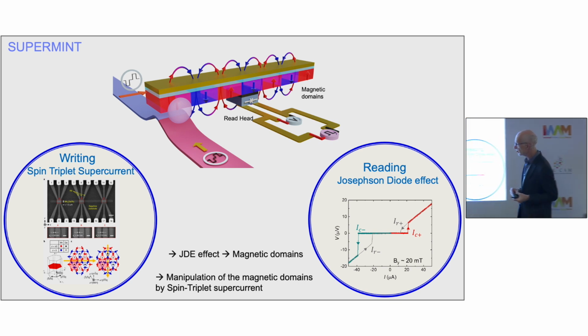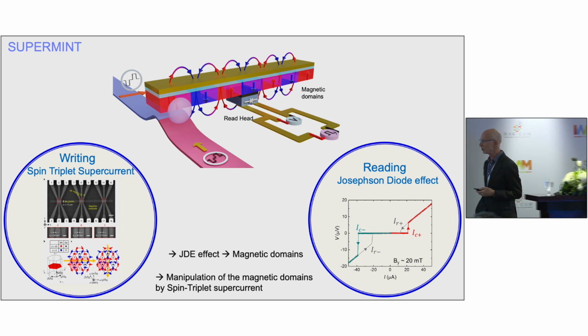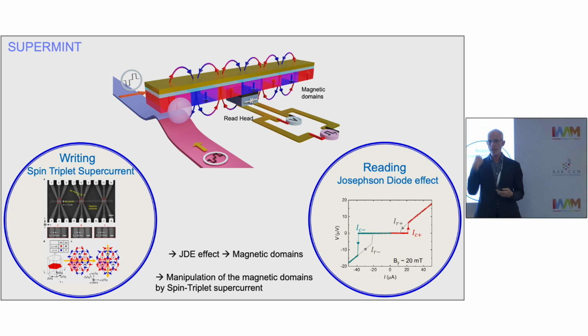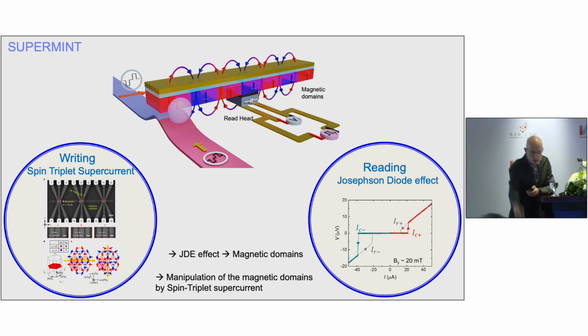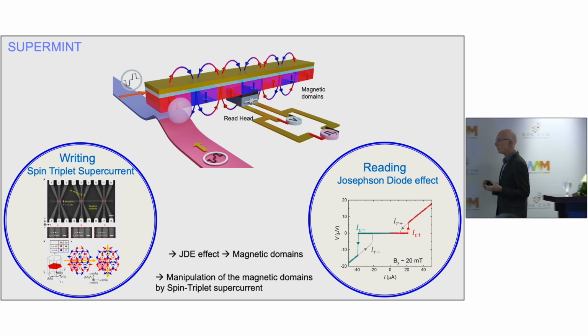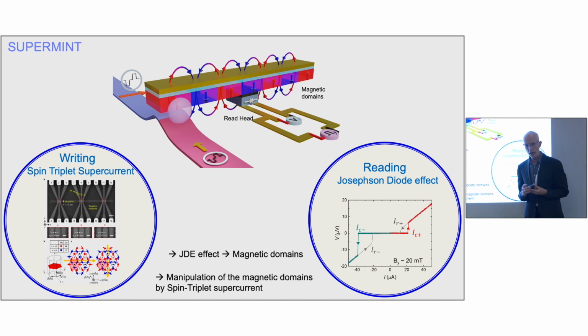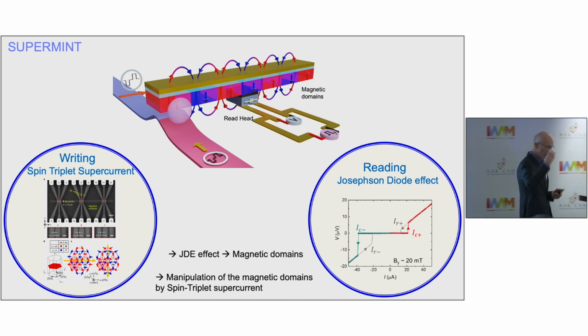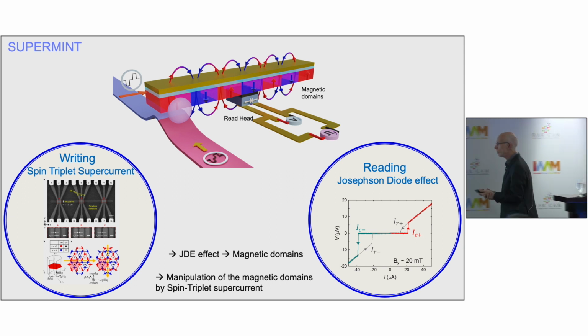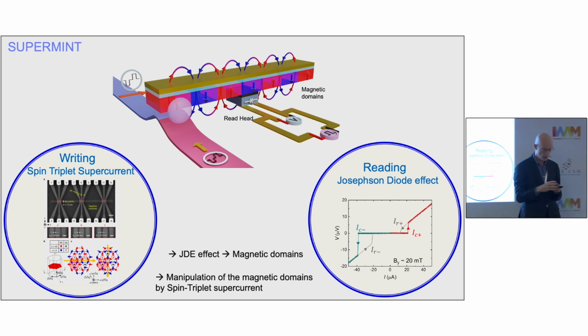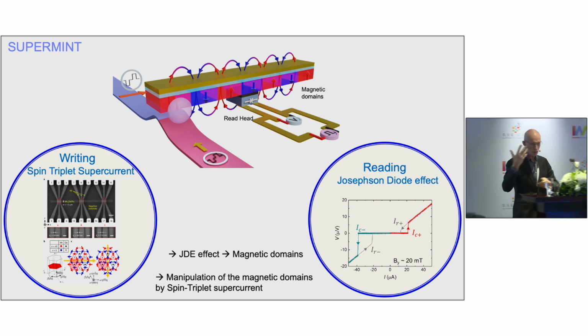However, it's possible, and this has been demonstrated over a relatively short period of time, that in systems with inhomogeneous magnetization, if you proximatize that system with a conventional superconductor like niobium or niobium nitride, then you inject into that system triplet pairs where the spins in the pairs are parallel. Of course, they can be in S equals 1, 0, or -1 state. Nevertheless, they have the potential to carry spin angular momentum.